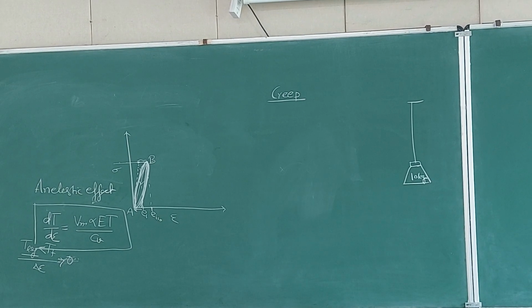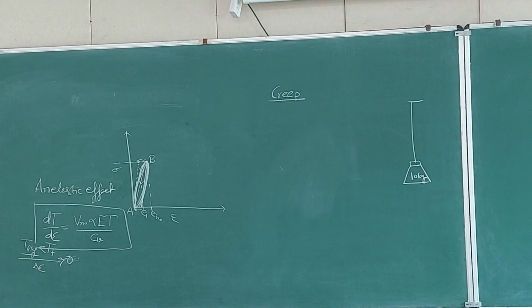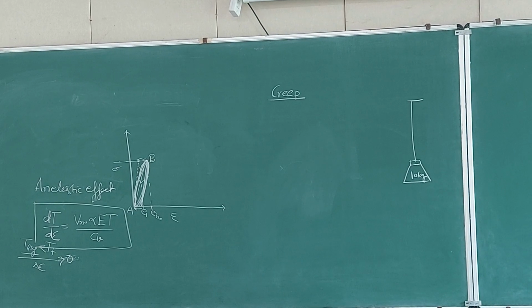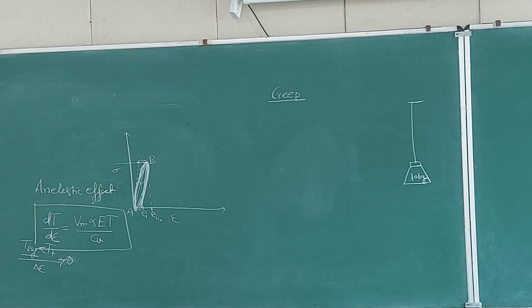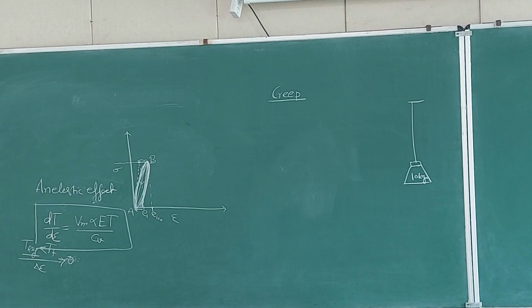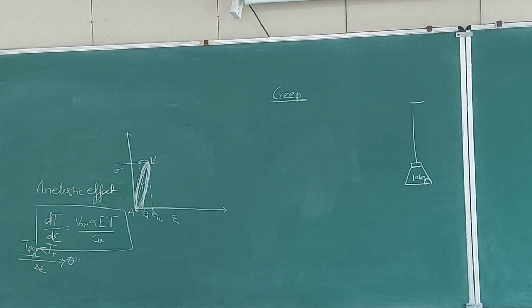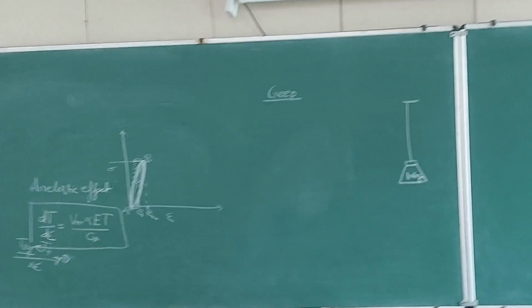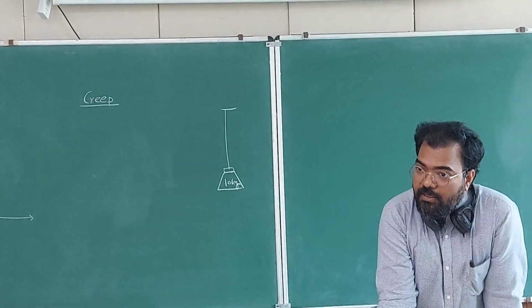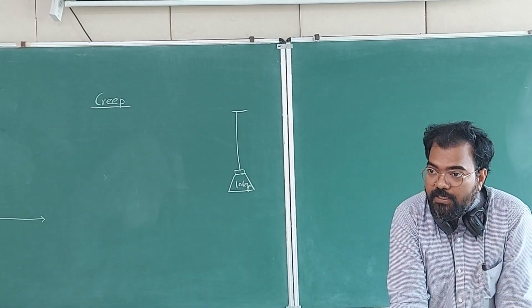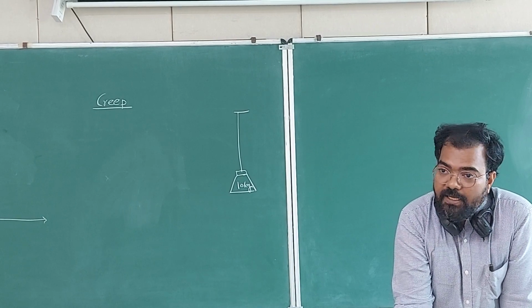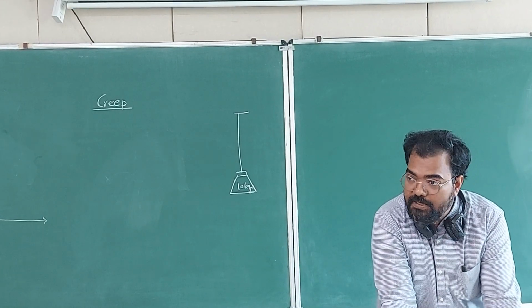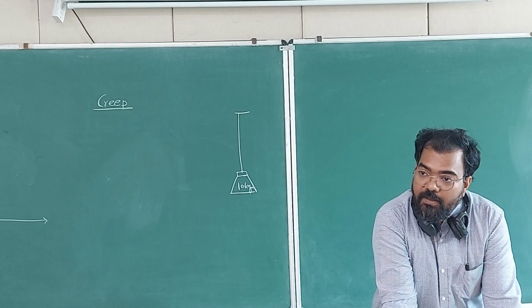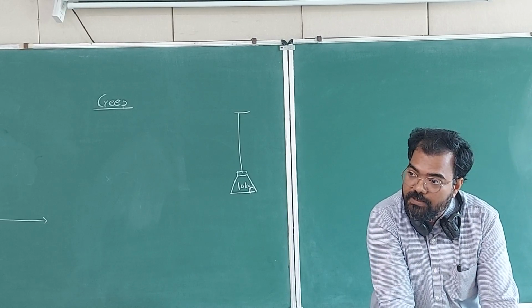Yes. Dislocations are blocked. And they are not able to move. And then there will be nothing happening. After 10 kg of load has been applied, some dislocation has moved, some deformation has happened. That is in the form of instantaneous strain. Now they are blocked. Now they cannot move. Okay, they have the tendency to move, but there is a barrier, and that barrier can be broken by increasing the stress or by providing a different path to the dislocation.